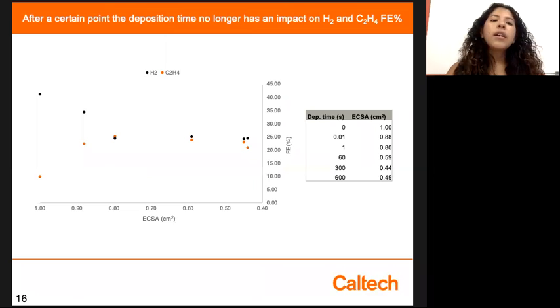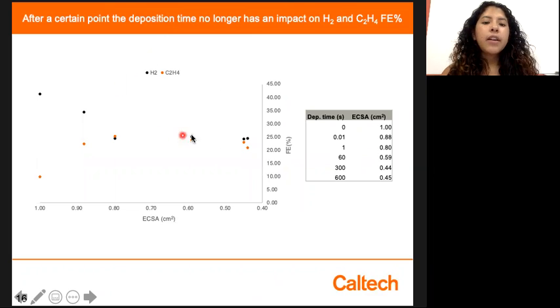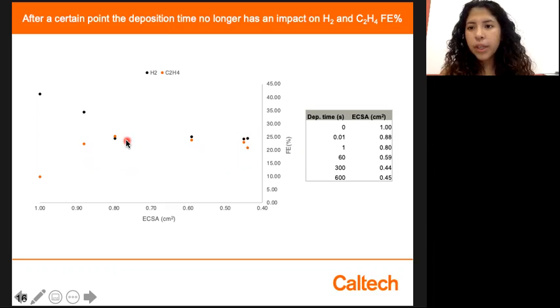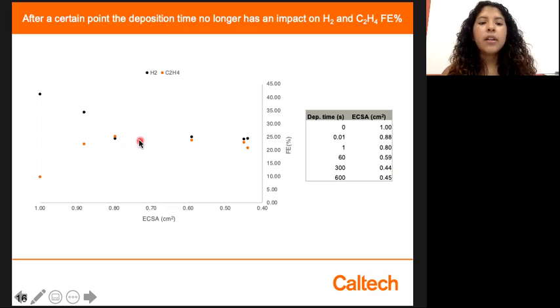We also wanted to look at how our films affect our product selectivity. And we saw, similar to the silver paper, that after a certain deposition time, there's a plateau in the selectivity of our products. This is important because then we know that after this point, no matter how long we try to electrodeposit the additive onto the copper, there will be no change in the selectivity of our system.